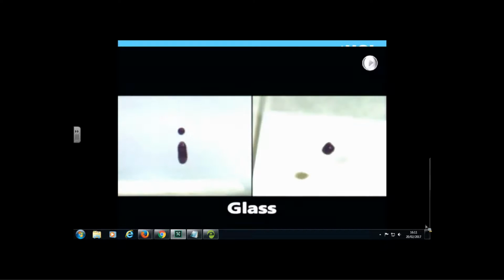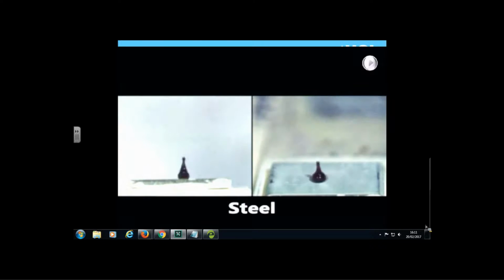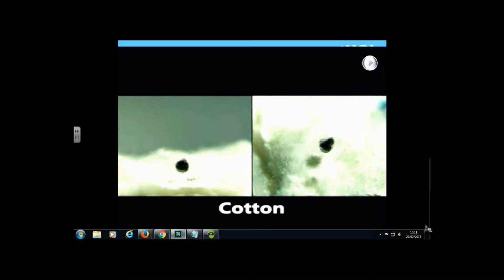However, if it's superhydrophobic, it's very, very water repellent, and the water droplet - in this case dyed with methylene blue dye - bounces on the surface. Even cotton, which is very difficult because it can absorb the force as you drop the water droplet, will actually bounce on these superhydrophobic surfaces. They're the ultimate in water repellency when coated with something superhydrophobic.